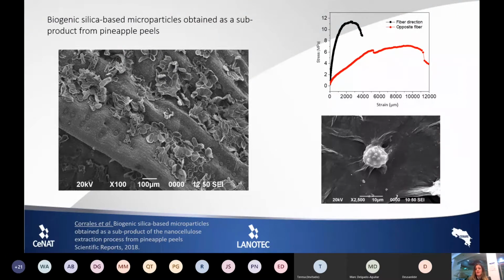So how this biogenic silica is formed, for example, is still a question. And we saw that this silica is aligned, for example, in one direction preferentially on the surface, giving mechanical strength in one direction, and is connected, if you see in this microscopy, by nanocrystalline cellulose. So we started, it was not just to analyze the material and to extract nanocellulose and to extract biogenic silica, but to look for a real application for these structures.